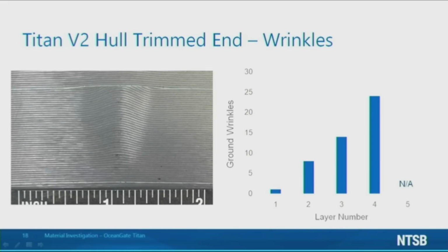A thorough examination of one of the trimmed ends indicated that the number of ground wrinkles increased with each successive layer, peaking at 24 for the fourth layer. No grinding was performed on layer 5 as it was the last layer.